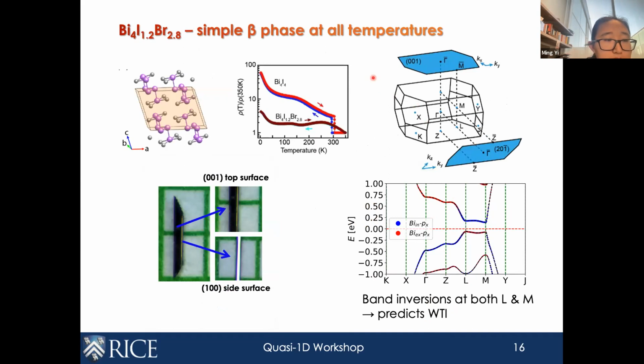So Bing's group and Fan's group worked together very hard to actually identify that if you substitute on the iodine site with bromine at some ratio, you can actually realize a very stable beta phase at all temperatures down to the lowest temperature they can measure. So to demonstrate that, you can see the contrasting transport behavior.